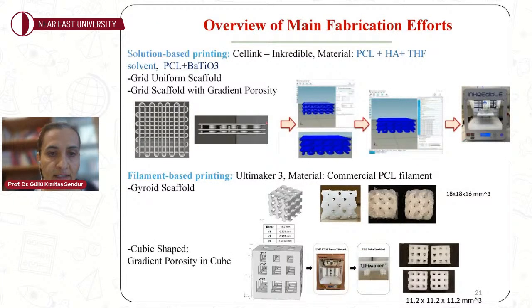So we can basically summarize our own fabrication efforts as solution-based printing that I've just mentioned, which starts with the drawing of a functionally graded scaffold, which are less porous at the center, more porous towards the outside in 3D. We transfer that as a 3D G-code into the bioplotter and get these scaffolds in 3D. We do also filament-based printing using commercial printers such as Ultimaker 3 in our lab, with both commercial PCL filaments as well as our in-house filaments, which are mixtures of ceramics and PCL.